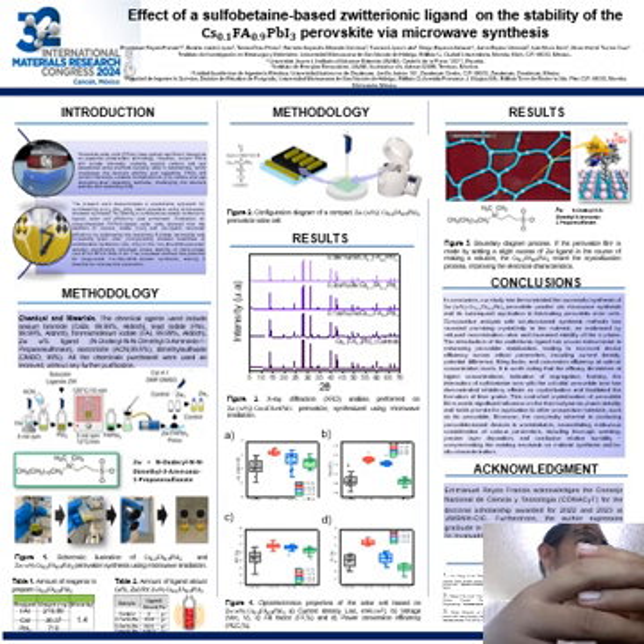So in this work, we demonstrate a sustainable approach for the synthesis of a specific kind of perovskite, cesium formamidinium lead iodide black powders, using microwave-assisted synthesis. With the addition of the sulfobetaine zwitterionic ligands, the solar cells' properties were enhanced. The evaluation of the pre-synthesized formamidinium iodide-based solar cells shows firstly, and then we add the cesium iodide. Sorry for that.